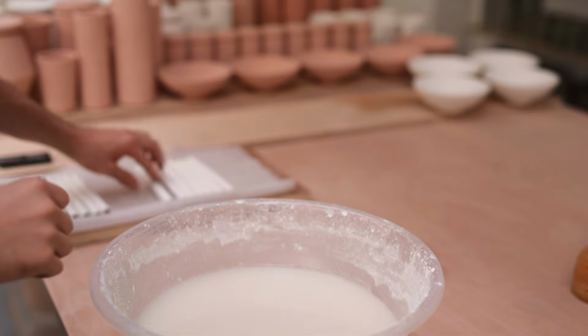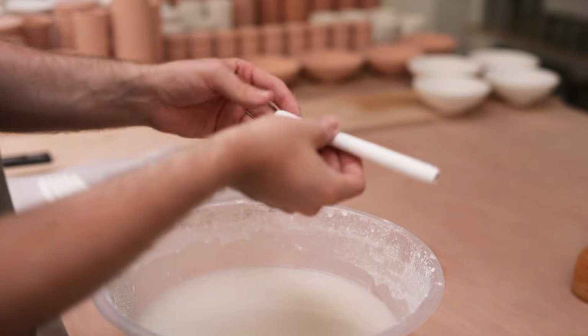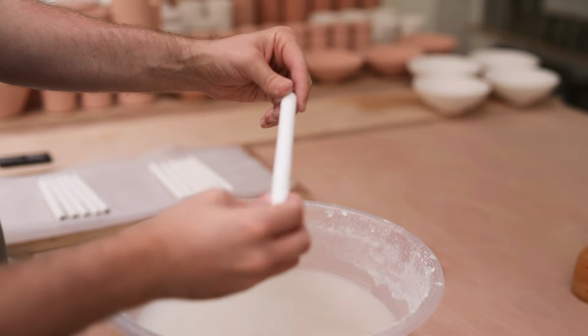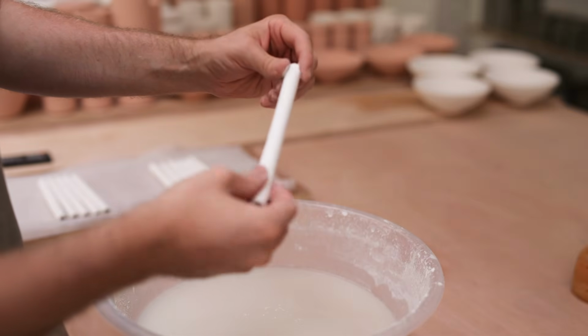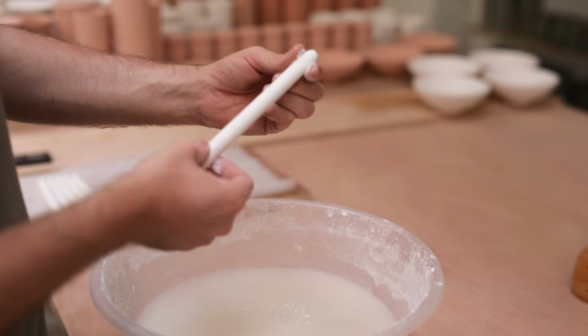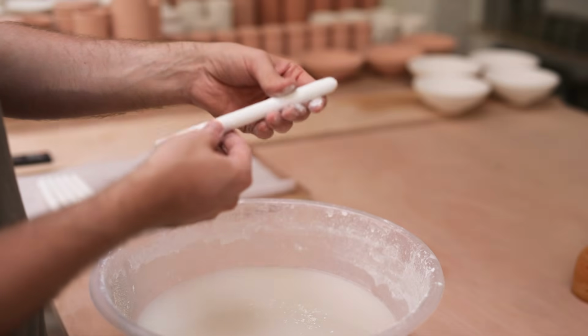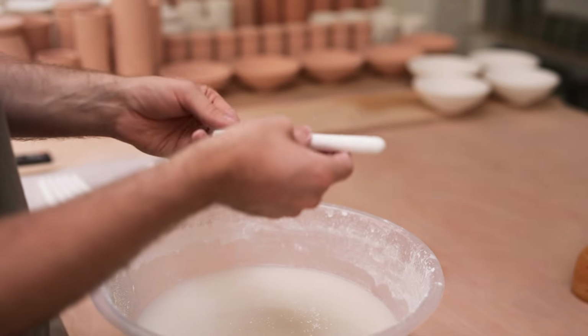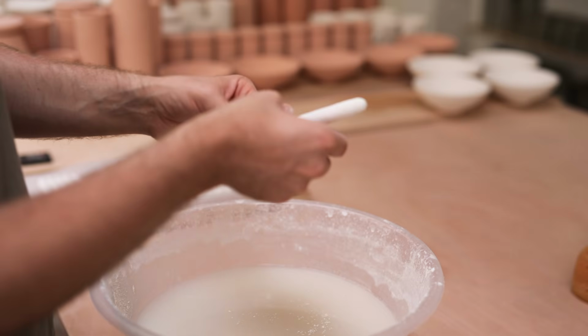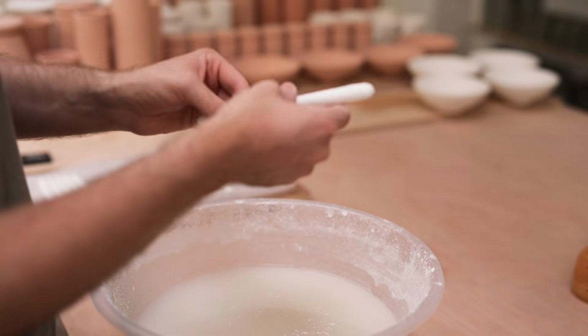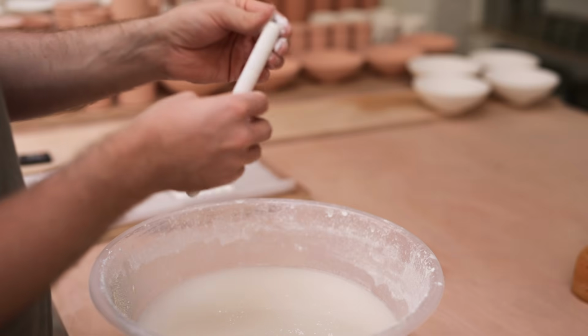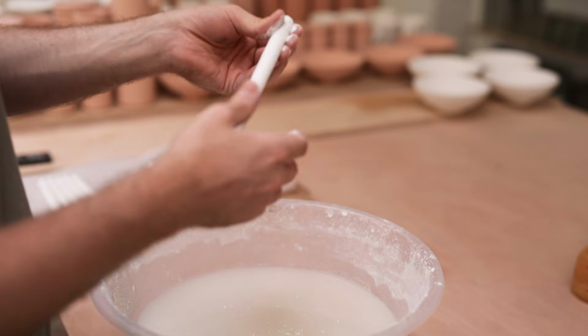And here's another pen, this time coated with a white, which is the exact same glaze recipe, just without the red iron oxide. This will fire a sort of grey-white hue. It certainly won't be as vibrant as the white that's seen here, but they'll have a lot more depth, and they'll be covered in tiny speckles of iron, a result of being reduction fired in a gas kiln.